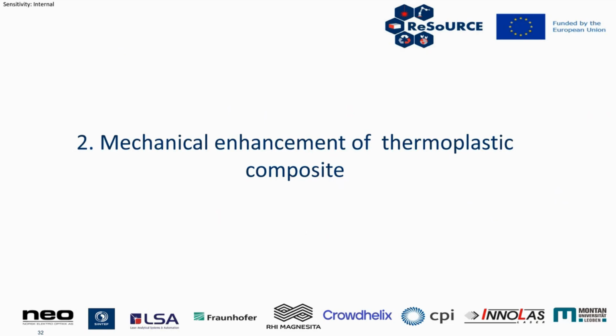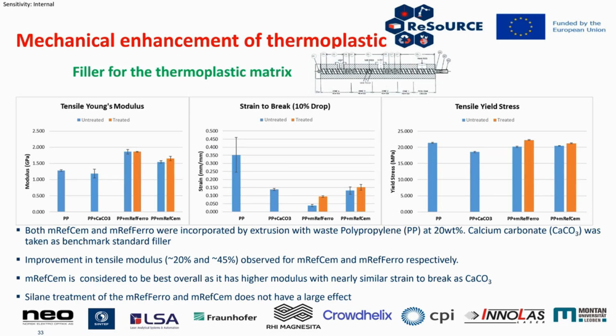Another test we looked at was, could we use it as a mechanical enhancement for thermoplastic composites? So for this test, we extruded it in polypropylene at 20wt%. You would usually use calcium carbonate as a filler in this instance. So looking at how the mRefCem and MREF ferro affected those results.